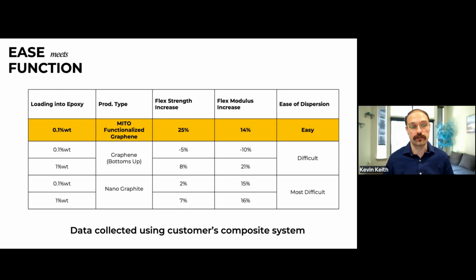Now, when you plug this functionalized material, these GR2Ms, into a customer system, what we found is that when you're comparing graphene, a bottoms-up graphene, or a nanographite, which is a material that has more than 10 carbon layers, and it's usually considered really chunky, think pencil lead, those are really hard to disperse and to get integrated. And so in order to do that, we actually had to 3-roll mill everything because they just disperse so poorly. Our chemistries and our functionalization, the way that we tailored it to this system, we could do a shear mix, but that wasn't cutting it for the other ones. And so you'll see here that whenever you actually do the formulation with the GR2M, the graphene material, and you pick the right buckets to go into the system, you get the property increases that you're really looking for instead of trying to brute force your way through it.